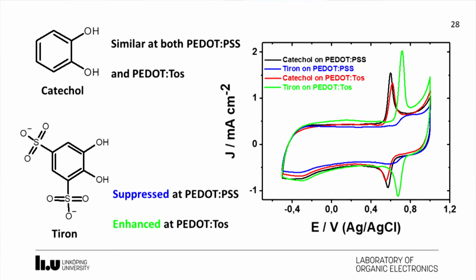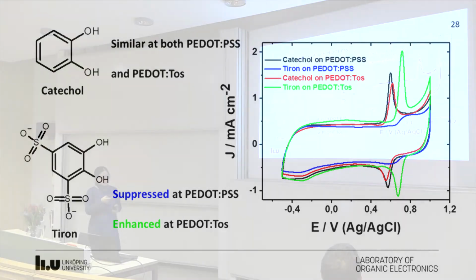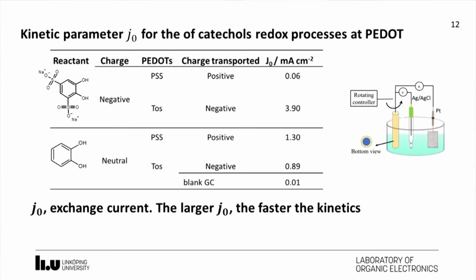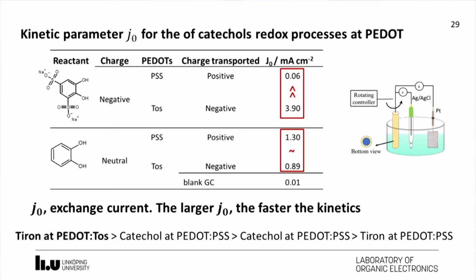But on tiron molecule reactions, we found that the peak current was significantly suppressed at the P-dot PSS electrode, but enhanced dramatically on the P-dot TOS electrode. This initial result shows there is ion-selective electrocatalysis, as mentioned before, and we studied the kinetics to prove that exchange current can be a probe for the reaction rate. The larger the exchange current, the faster the kinetics or the reaction rate. We found that on neutral catechol, both polymers show similar or close values of the exchange current. But on negatively charged tiron molecules, on P-dot PSS, the exchange current was significantly smaller, while on P-dot tosylate, it was about 2 orders larger. So this further proves the ion-selective electrocatalysis.